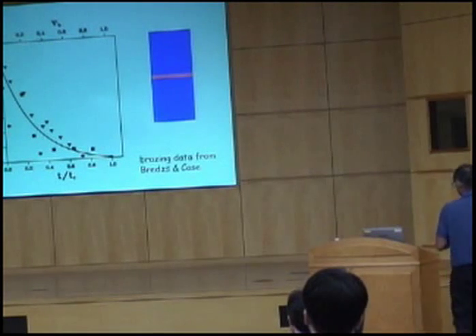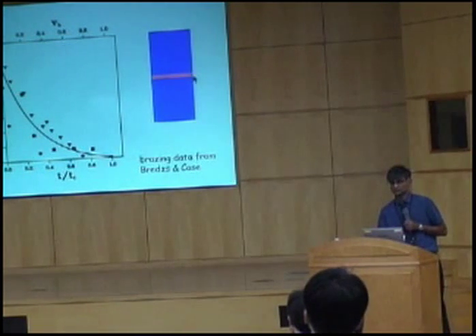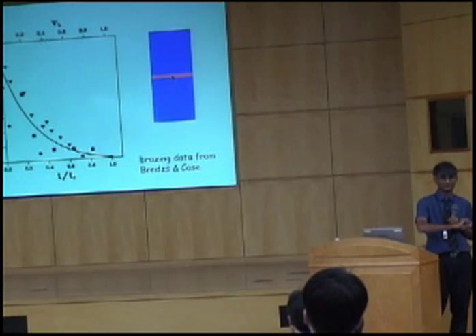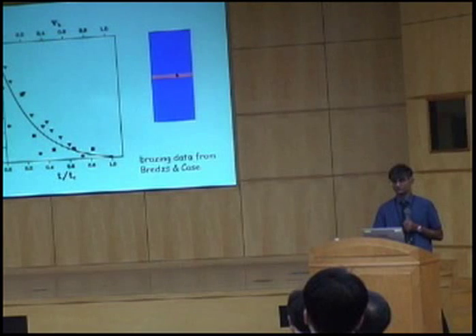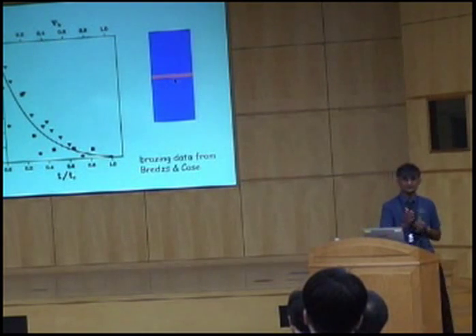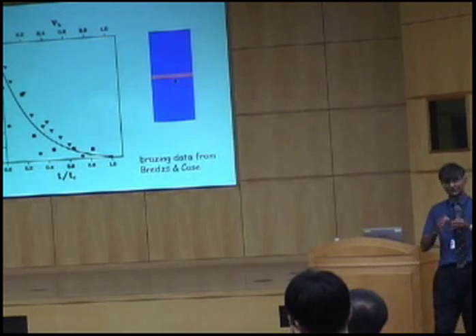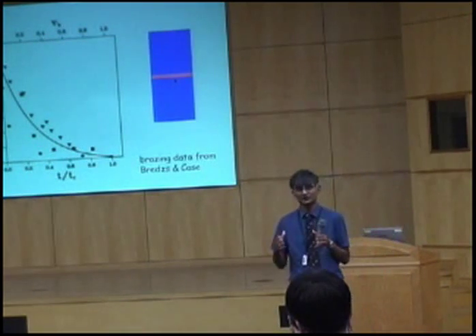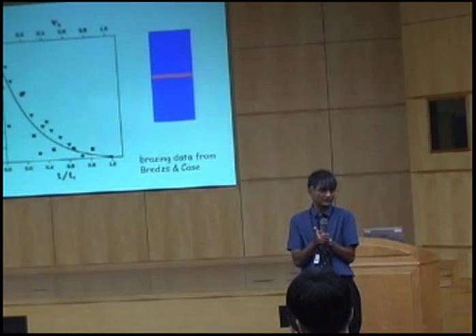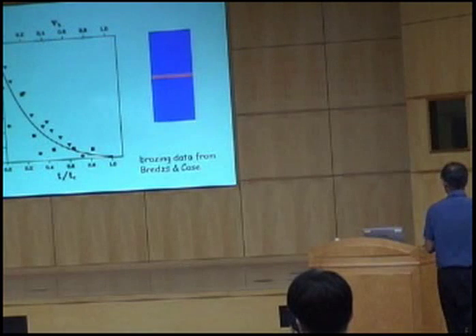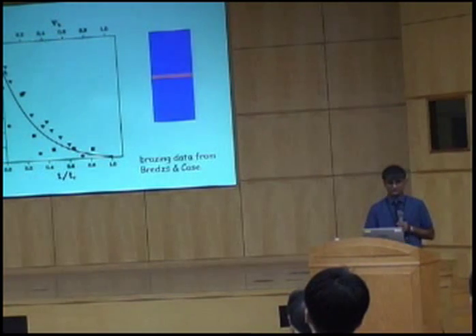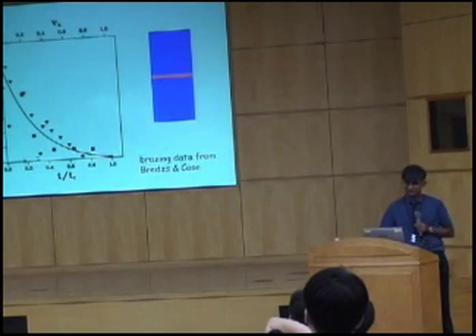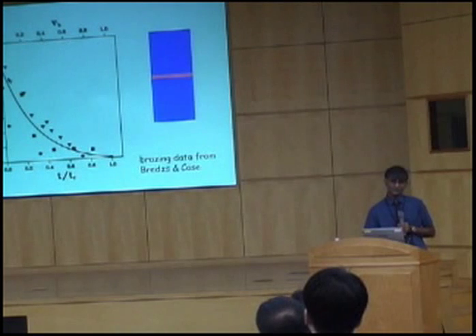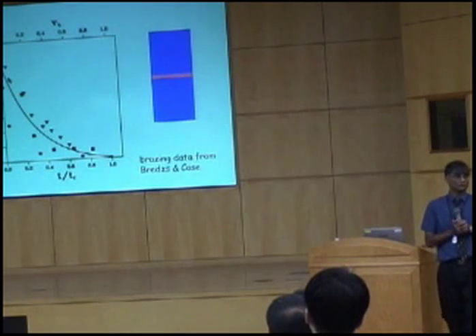Well, the answer is that this layer of polymer has to be very, very thin. When it is thin, it is stopped from deforming by the steel which is around it. So that's constrained. If you make your glue thinner, your joint actually becomes stronger. Okay? Because the steel stops that glue from deforming. Okay? And you can see that in this graph over here, that as I increase the thickness of the glue, the strength drops dramatically. Okay? So this is the strength of the glue by itself. It increases here because the surrounding steel stops the glue from deforming.